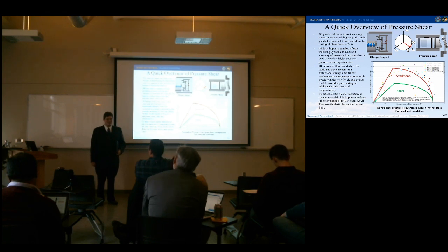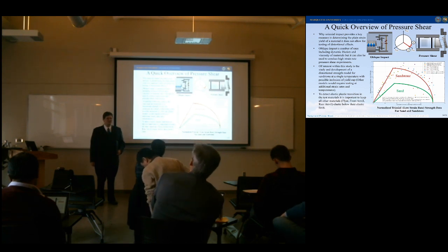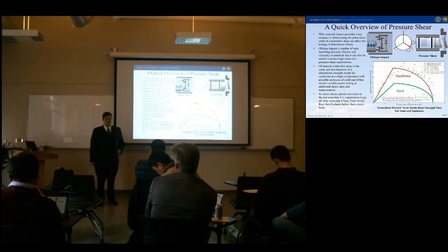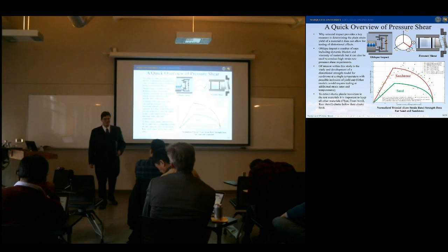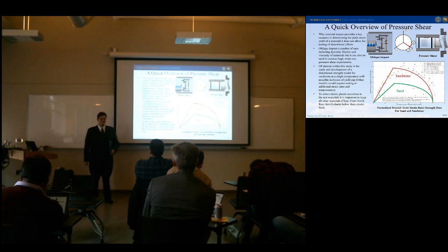I think for most people, they've looked at sandstone and they've said, well, A, pressure shear is relatively new in the shock field. But B, in order to try and get pressure shear on a heterogeneous material, that's pretty difficult. I think one of the first heterogeneous samples I've seen was here at Marquette in my reviews of shock. I think the first one I was exposed to was Jeff, who did a mesoscale. There may have been some more at SCCM and stuff, but I think that's pretty unique. A lot of people just do really thin samples in pressure shear and of very homogeneous materials.